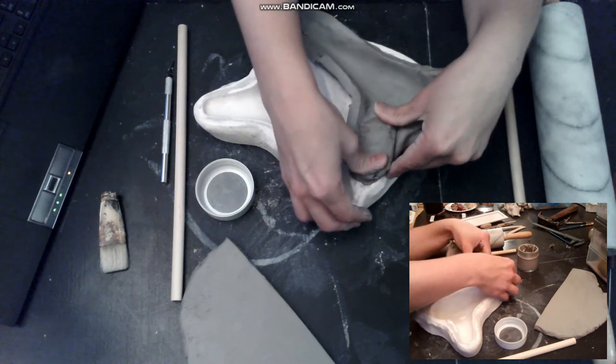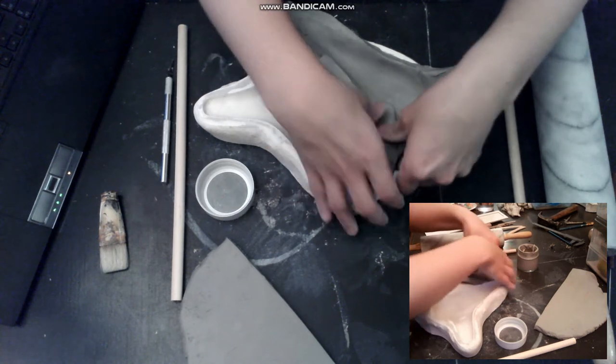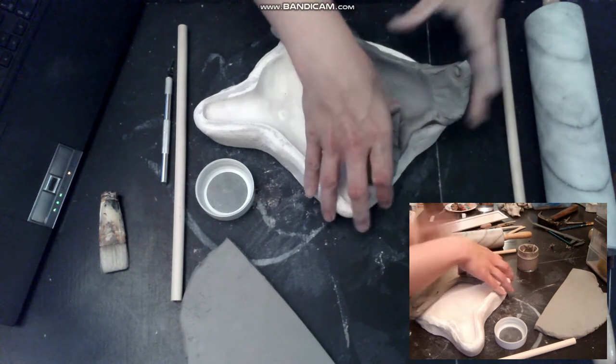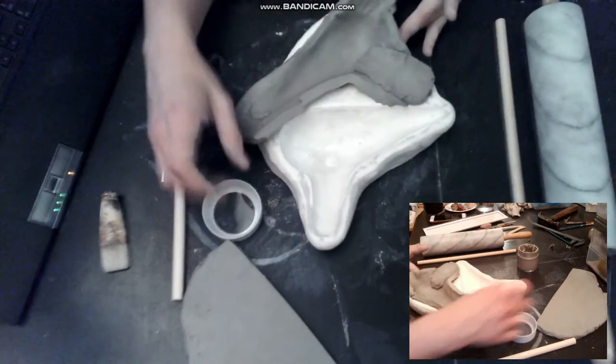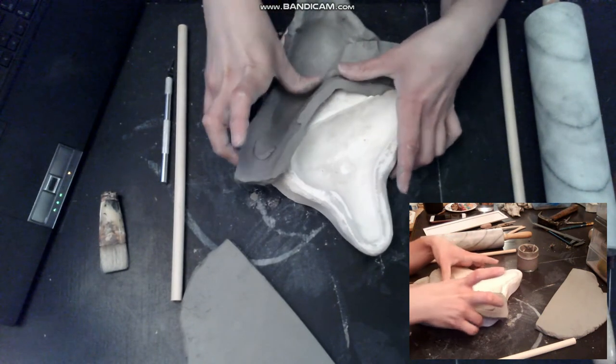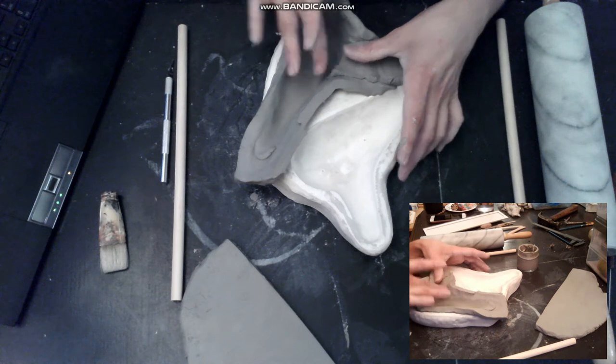I am filling the mouthpiece with more clay. I added slip just before because I had some occurrences where pieces exploded into the kiln at the same place. So it's very important to add slip at this step.